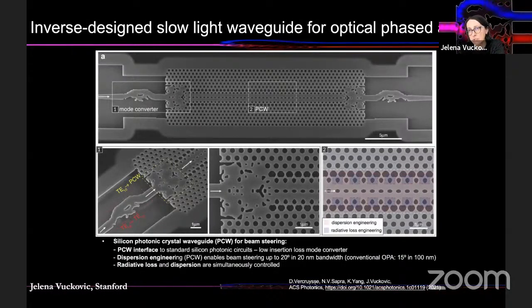But here we've shown that we could do it by this optimization approach, where we just let the computer search the whole parameter space until we achieve the desired dispersion. And that was achieved here, and it enables beam steering at the output by 20 degrees in a 20 nanometer bandwidth. So it's really a very large group index, slow group velocity in a large range of wavelengths, which would enable optical phased arrays that are much more compact and practical than the state of the art. So this is the optimized photonic crystal structure, and you see a lot of different elements that are interfacing this photonic crystal circuit to the surrounding traditional silicon structures, converting modes of traditional silicon waveguides to photonic crystal structures, and doing all the mode matching.